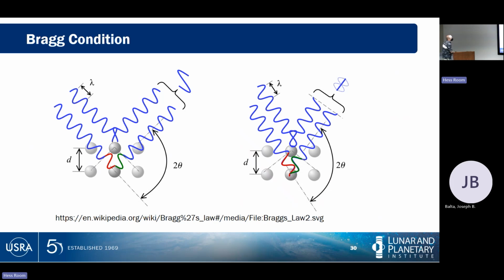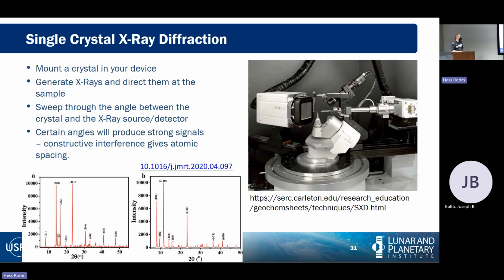It requires you to know your X-ray wavelength, and it requires you to know the angle that you're shooting at. In single crystal X-ray diffraction, you literally take your crystal, spin it around by hand in a machine that's firing X-rays at it, and this analyzes the spacing of the atoms along the different axes and allows you to uniquely identify the crystal structure. These are powdered X-ray signals down here, and we have one of these that's been rolling on Mars for more than 10 years now. The Curiosity rover has one as a mineral identification tool. In powdered XRD, you conduct a single analysis where you vary the angle. As you sweep your detector across the powder, you get strong spacings and weak spacings that show up as peaks that you can use as identifiers for certain symmetry planes in your mineral.